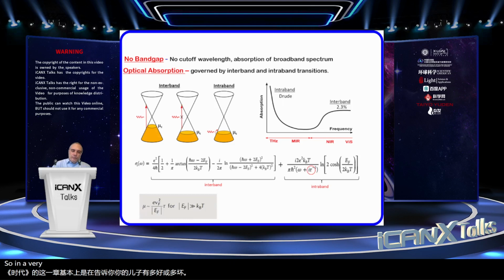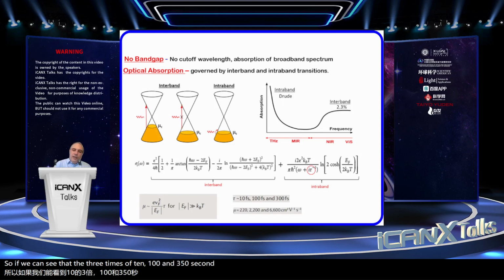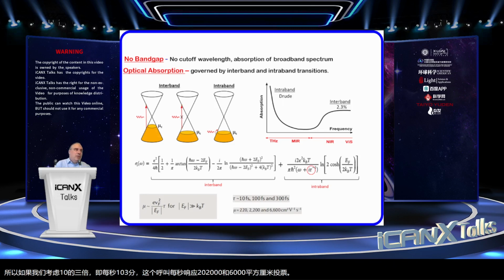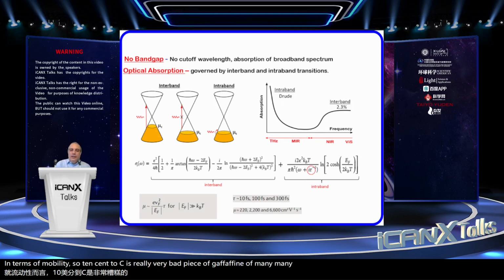So in a very simplistic way, not fully correct, but good to get an idea, the mobility of your device is inversely proportional to the doping and directly proportional to the scattering time. So the longer the scattering time, the better your material. If we consider 3 times of 10, 100, and 300 femtosecond, this corresponds to 200, 2,000, and 6,000 centimeters square per volt per second in terms of mobility. So 10 femtosecond is really a very bad piece of graphene of many, many years ago. 100 femtosecond is a reasonably good piece of graphene that anybody can get nowadays. 300 plus femtosecond is what people are trying to achieve at the moment.